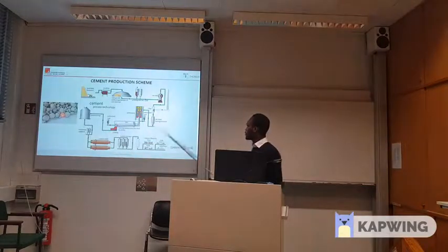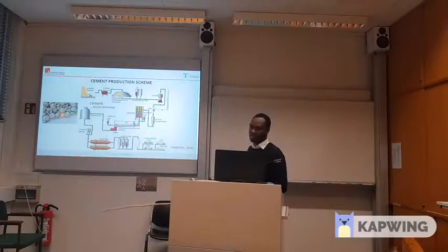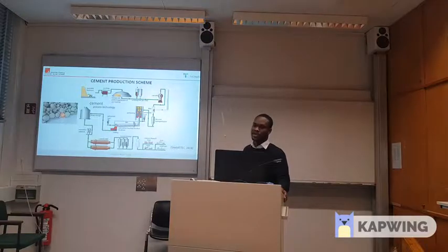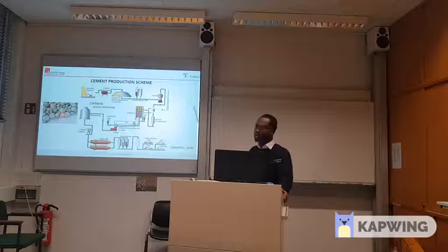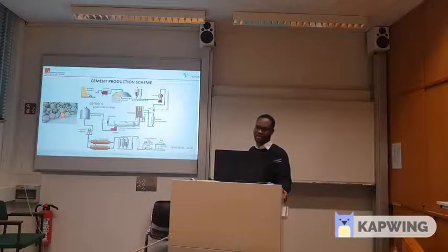And we come to the actual process where we are going to heat them up. The calcination is basically just applying high temperature heat to the homogenized material. Normally we apply temperatures above 825 degrees Celsius, and from literature, most companies try to burn around 900. Others could go beyond 900. But always the temperature is mostly above 825 degrees Celsius in calcination. That is why a lot of carbon dioxide is also released from this whole process.